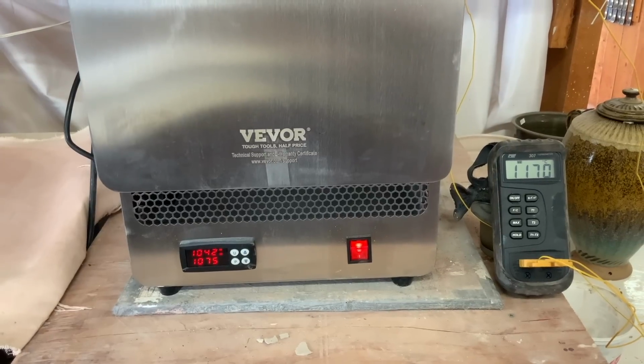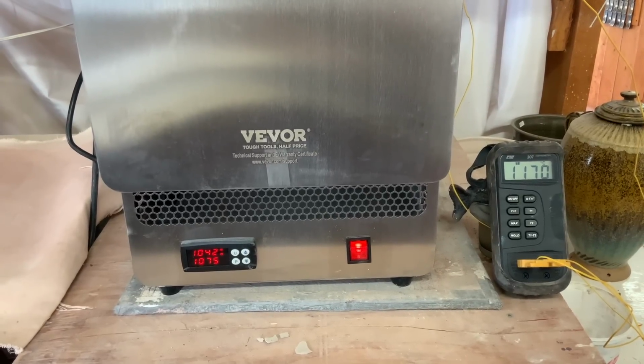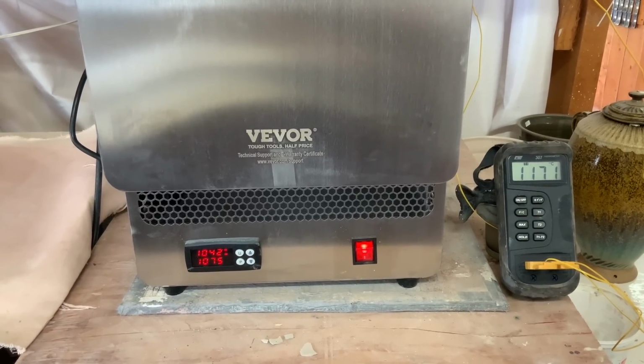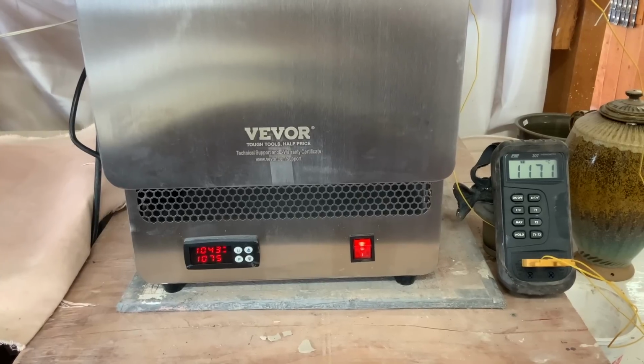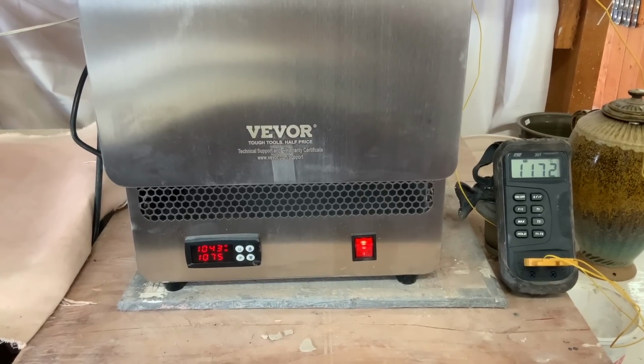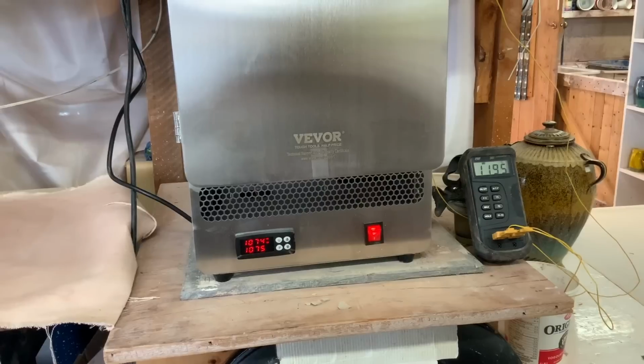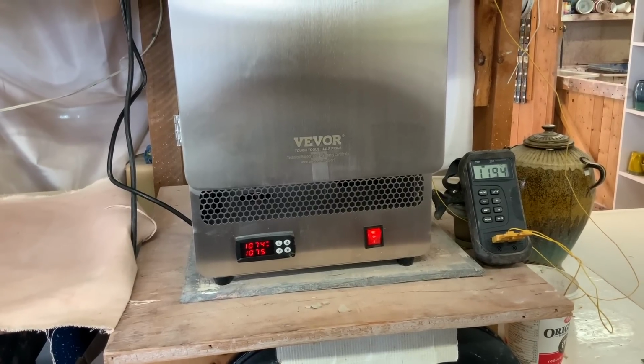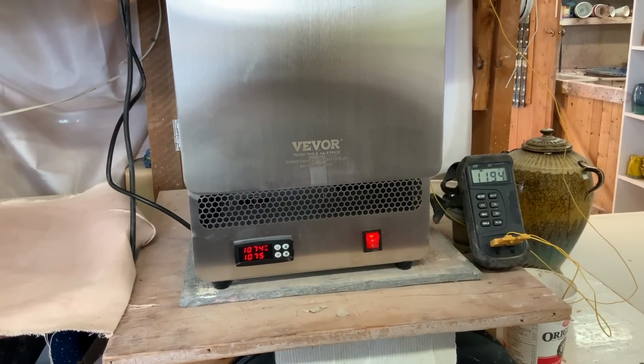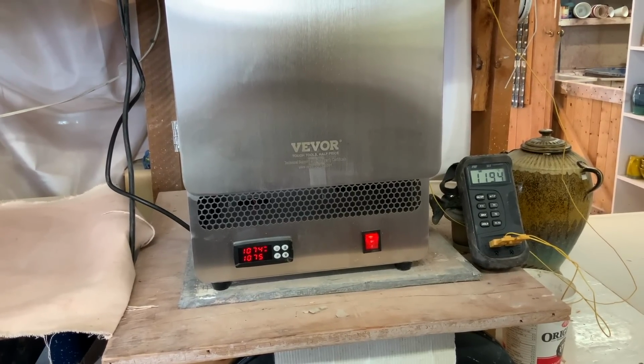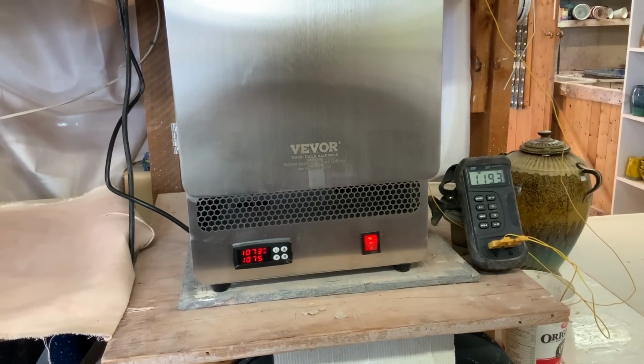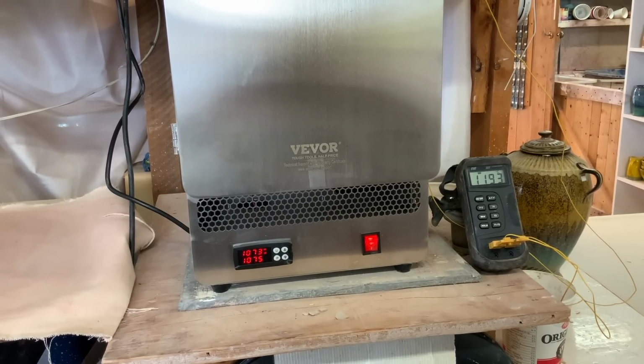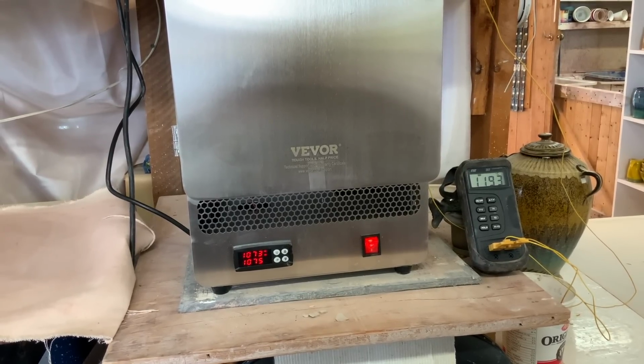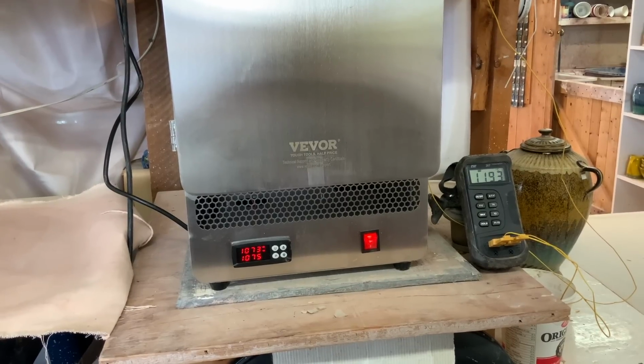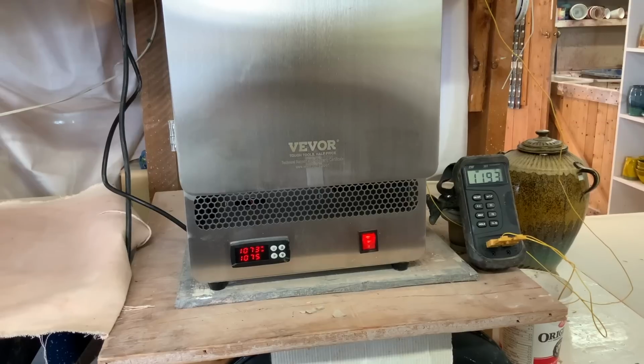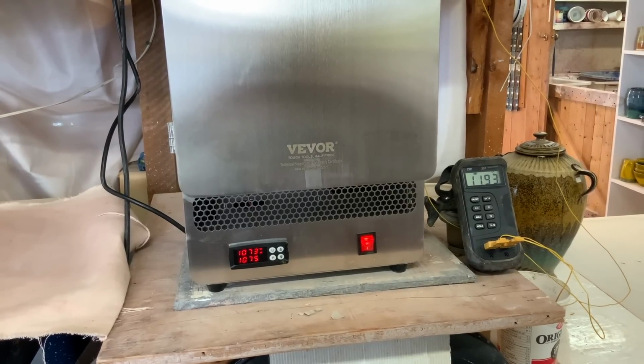So we're going to try, and we've got my safety temperature in there at 1200, and now I've lowered it on the other kiln to 1075, and we should be there in the next 5 minutes. Okay, the kiln is only 1 degree off in its heating cycle, and it will hit 1075 that I've actually set it at. And the other one is reading 1193, which is below my safety temperature, because I didn't want to overfire this.